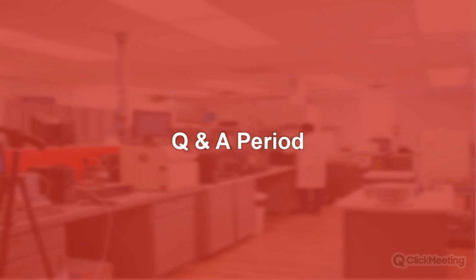If you need something quick or an estimation of those properties, and you've fully considered your dimensions and how the different time scales affect your results, you could consider a transient method, but with great care. And you would report that as effective or apparent with a description of why it is effective or apparent. That's really important. So many people just describe results as effective or apparent without a description, and it leaves the reader confused or assuming that it's as true as possible without a description of what makes it less true.